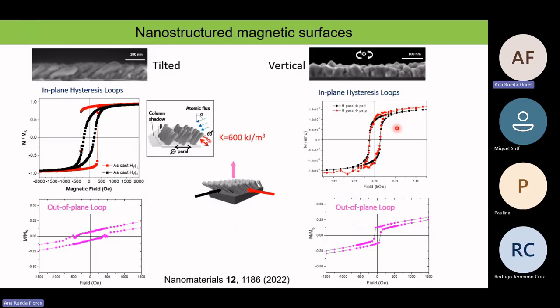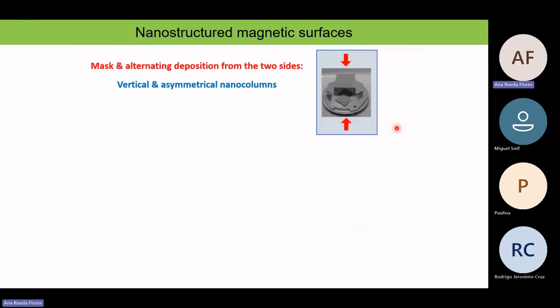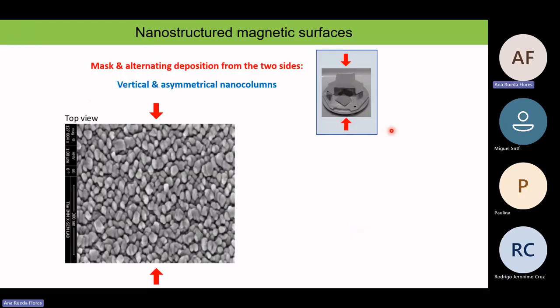And then we can do more, we can do funny things. For instance, we can use a mask while we are depositing, and we can deposit from one side of this tunnel or from the other side. So during the deposition, the substrate was in the middle of the tunnel. I just removed it a little to take the photo. And then by using this mask, we can have vertical pillars, but asymmetric in the plane. So they are elongated along the direction of the axis of the tunnel.